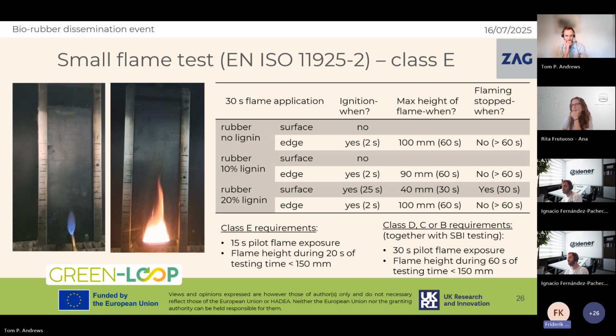The first test that we normally do with material that we expect not to be non-combustible is the small flame test. This is a standardized test. On the left, you can see the attack on the sample. In the middle is the sample, and the attack with flame. The exposure is either 15 or 30 seconds. It depends on what our targets are. And then we observe whether the material has ignited and whether the progressing of fire was big or not, and when the combustion stopped. So for Class E requirements, it's 15 seconds pilot flame, and for Class D, C, or B, so the higher classes, it is 30 seconds pilot flame exposure.